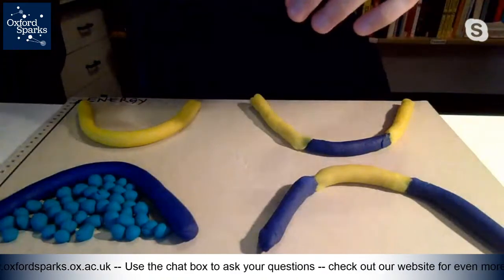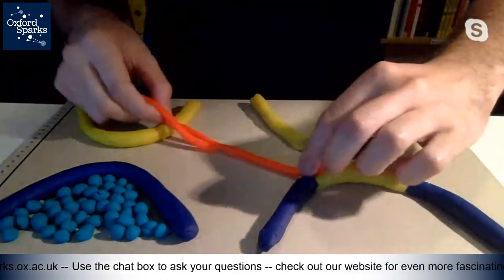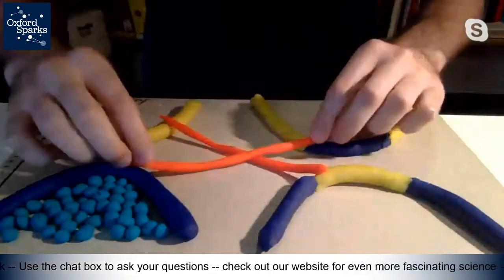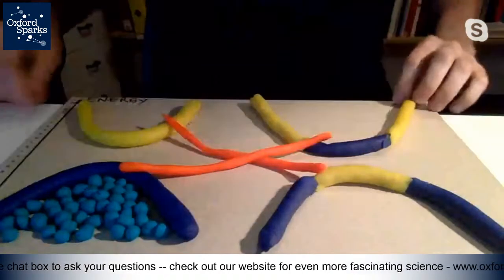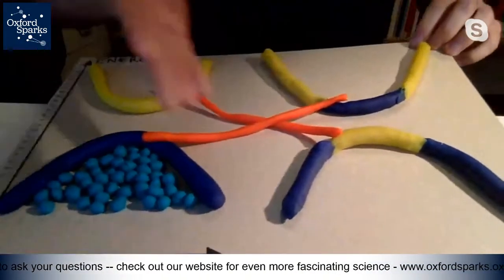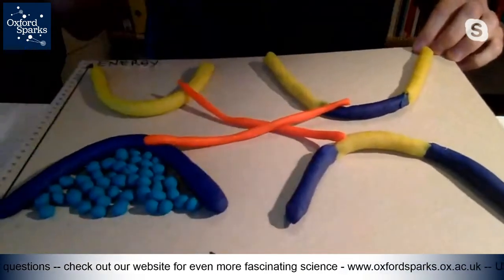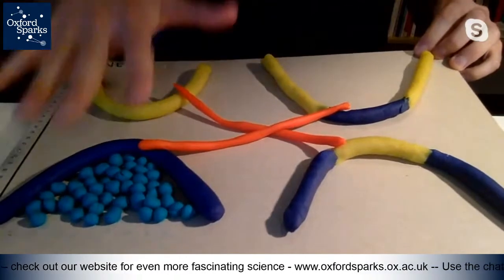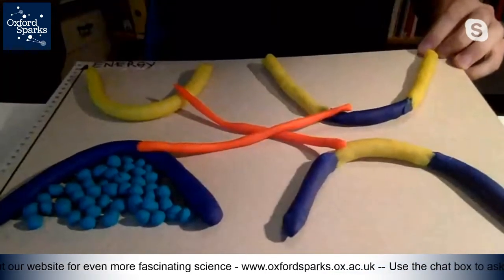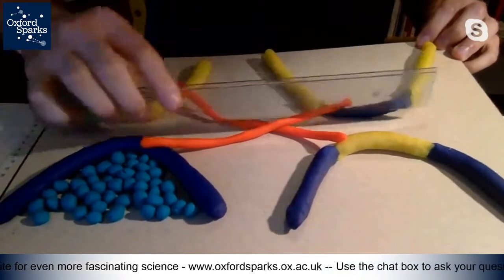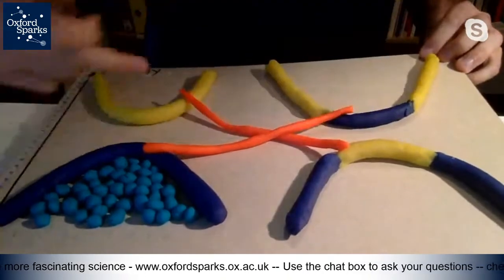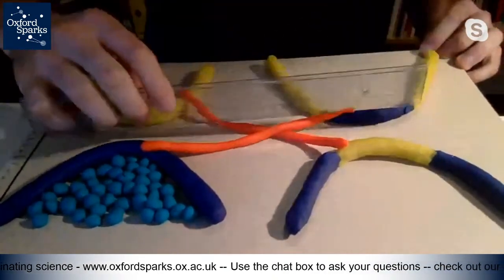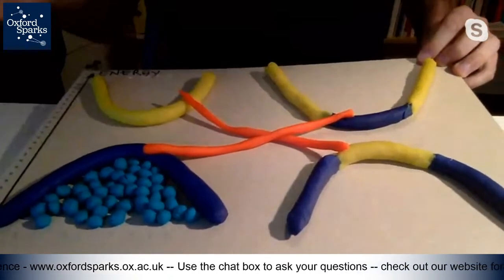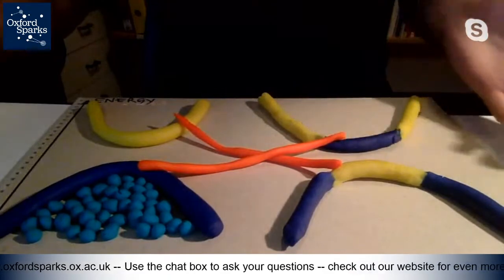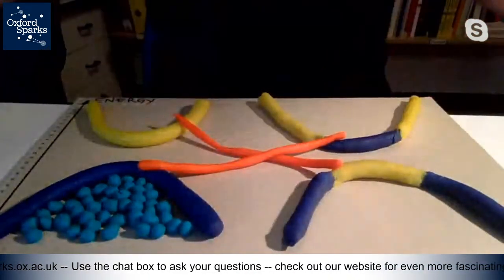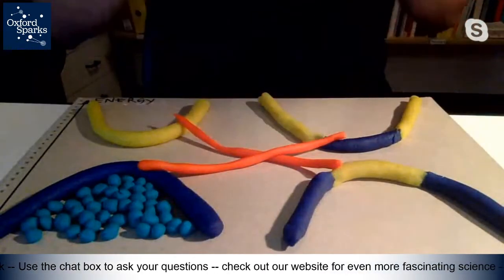And what happens is that then at the edge, we have states that have to connect the yellow with the yellow and the blue with the blue. So we have something like these red states here. And those states are localized precisely at the edge, hence the name edge states, between the trivial insulator and the topological insulator. And remember, we said that the Fermi level is around here. So while the two bands are not conducting, they are insulators, these states are precisely at the Fermi level and they can conduct electricity. So we have this very peculiar situation where the bulk is insulating, but we have edge states on the boundary that can conduct electricity very efficiently.